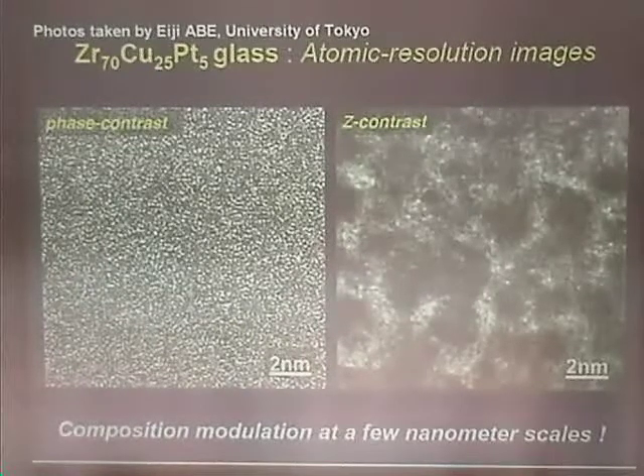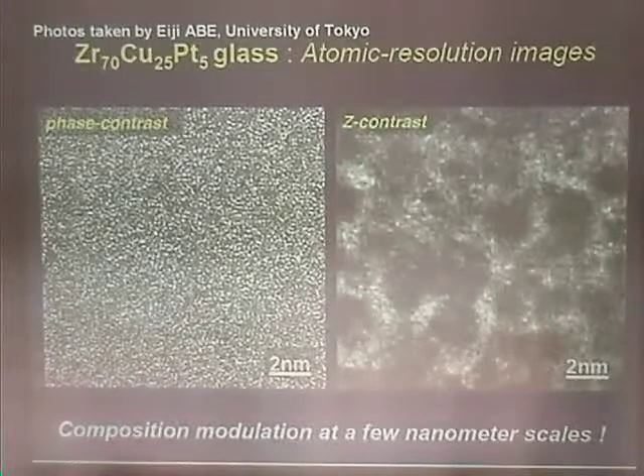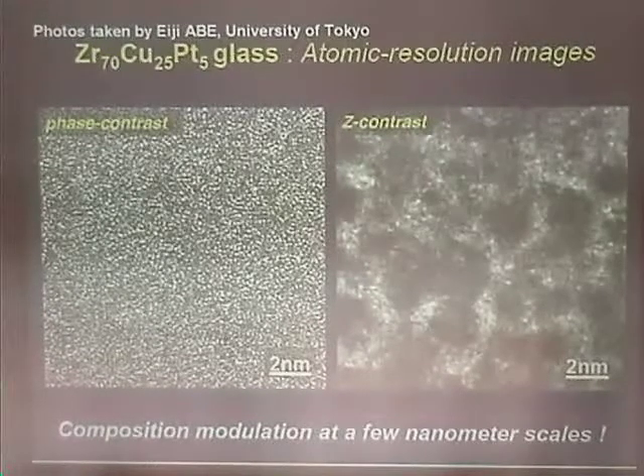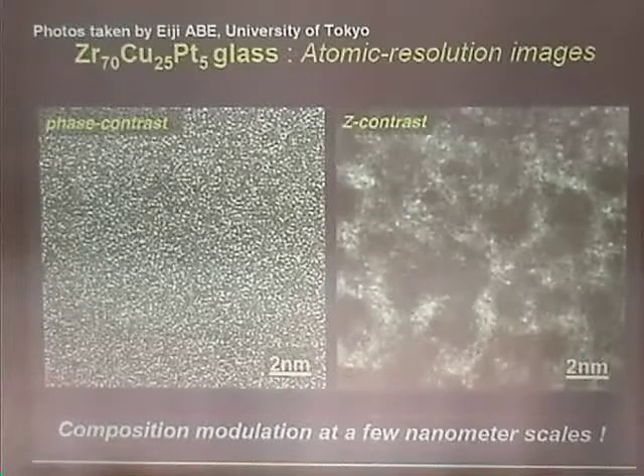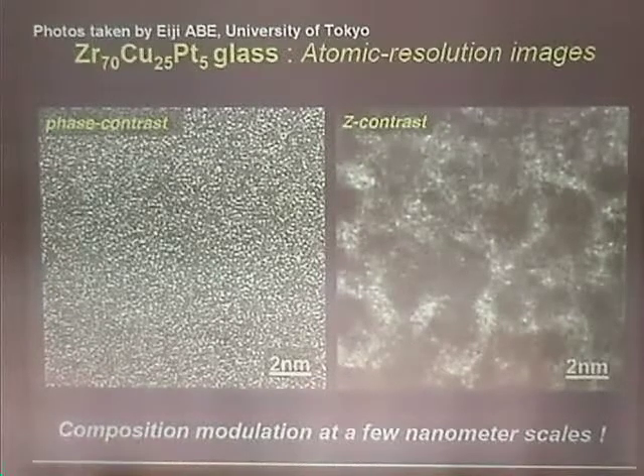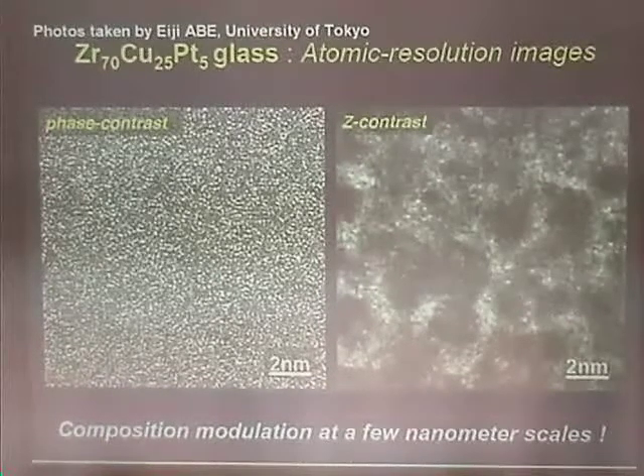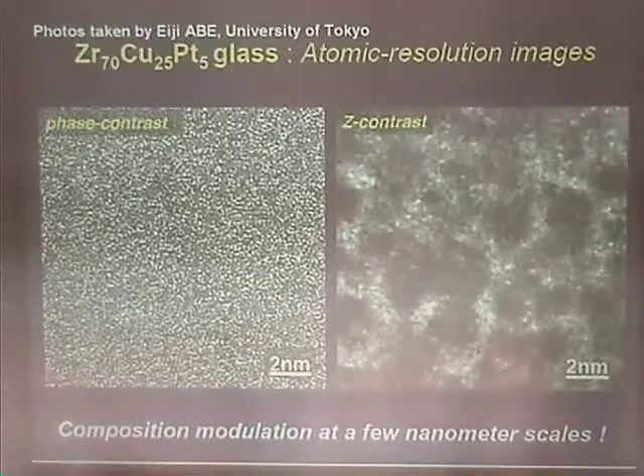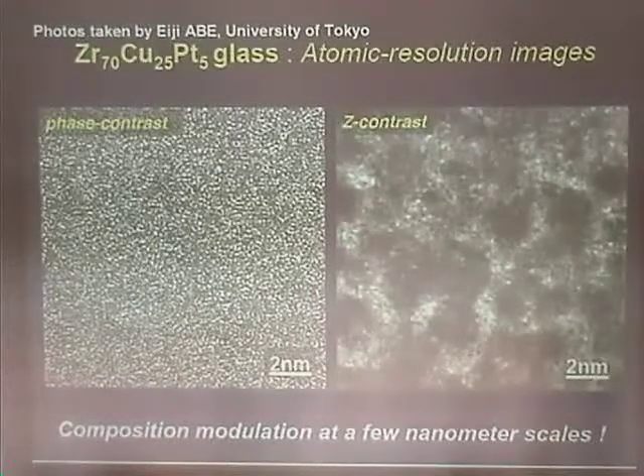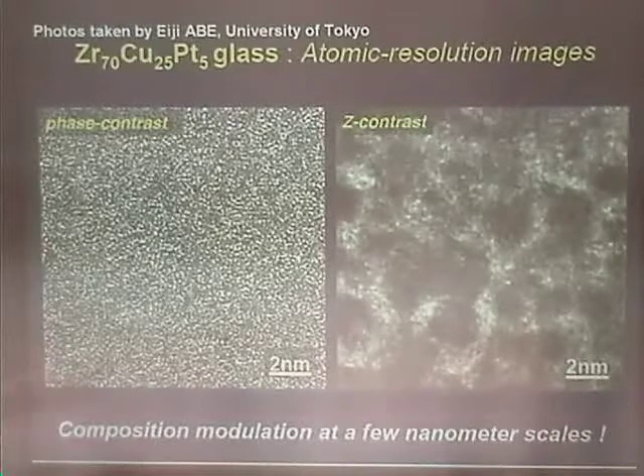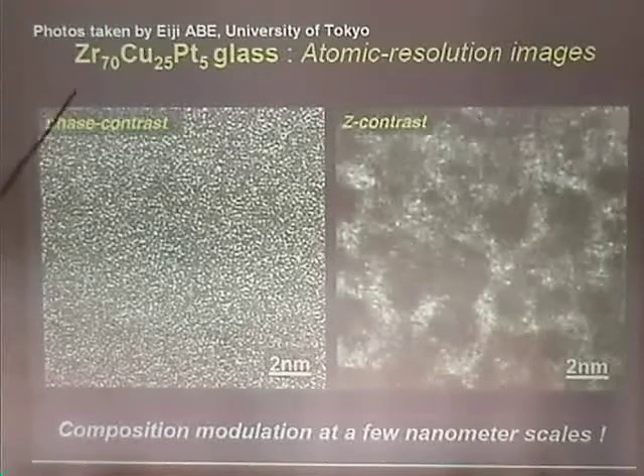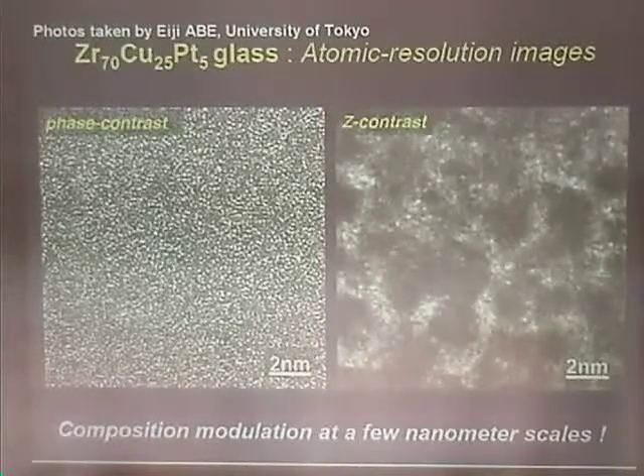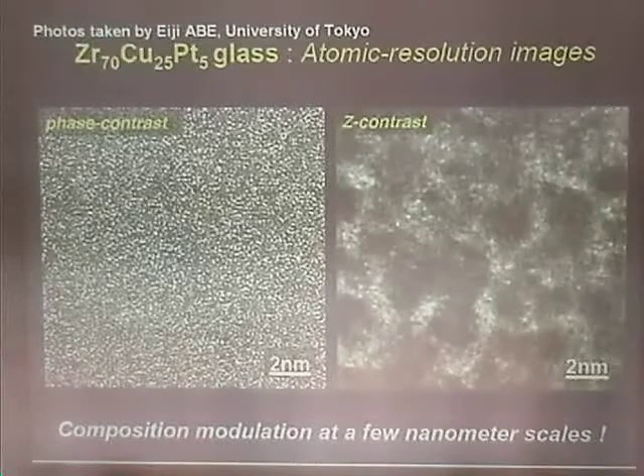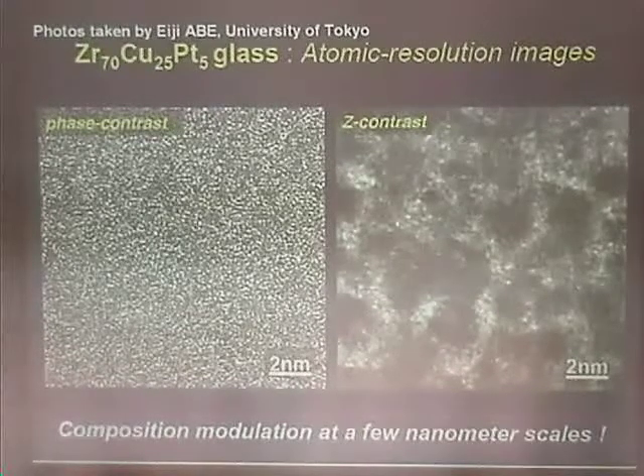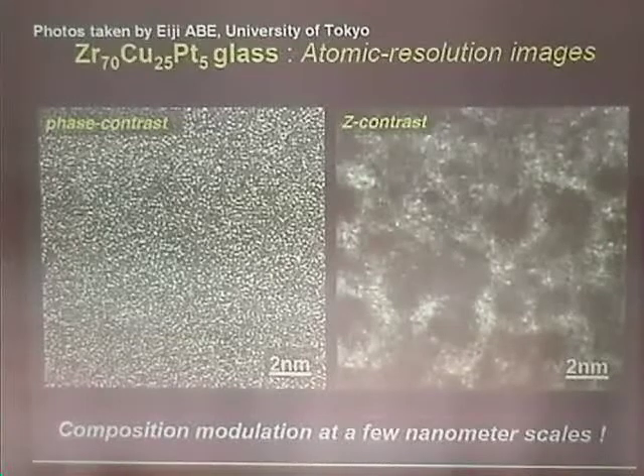I'm just looking at the length scale here, maybe 2 to 4 nanometers, and that seems intriguingly close to the length scale that you predicted from your other work, which was, I think, 3.5 to 5 nanometers. Is that just coincidence? No. The system is not different. So this is a zirconium. So this one didn't have that other length scale, right? The zirconium-based glasses didn't have that other length scale.